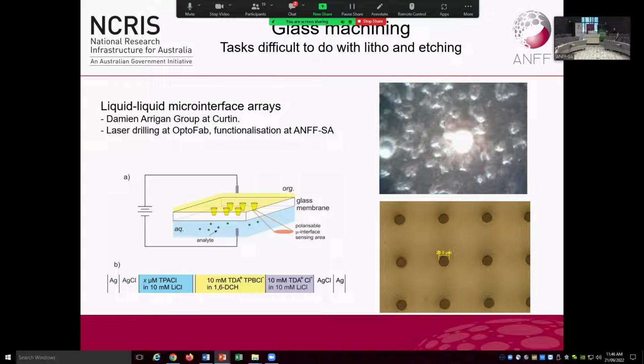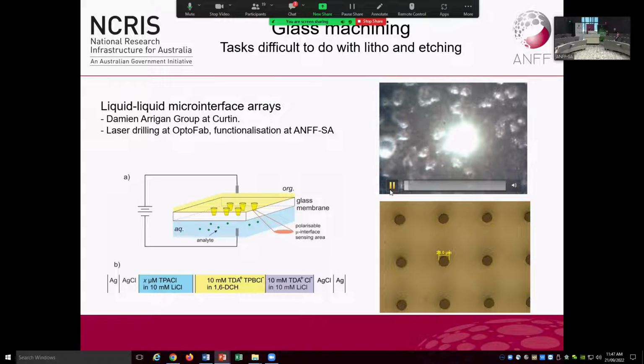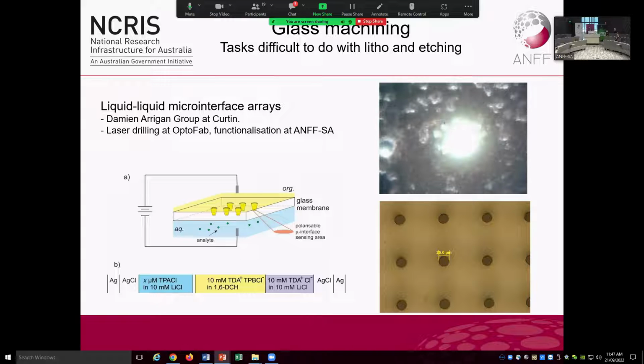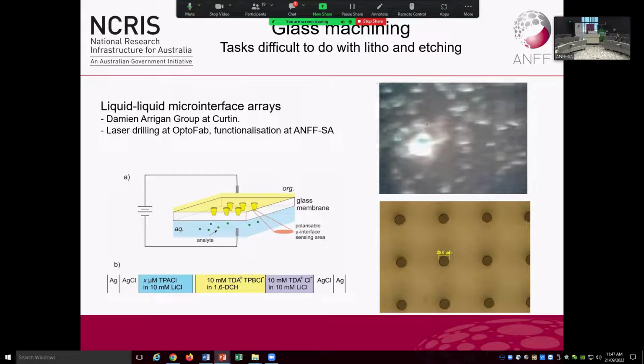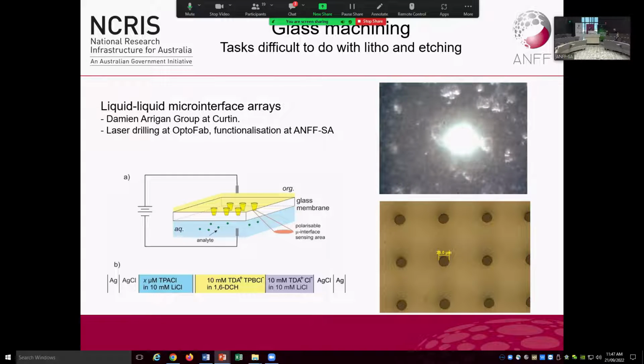And that's very fragile to try and put in a mask aligner. So one little example of something we do. Here we're drilling some little 25 micron pores through 100 micron cover slip glass. And with this, the group at Curtin is doing some liquid separation, because they will make one side of these pores hydrophobic and one side not, and they can do some chemical migration through them. The chemistry is up to them, but the processing here is something we can do with a little UV laser to make something that's very difficult to do otherwise in the clean room.